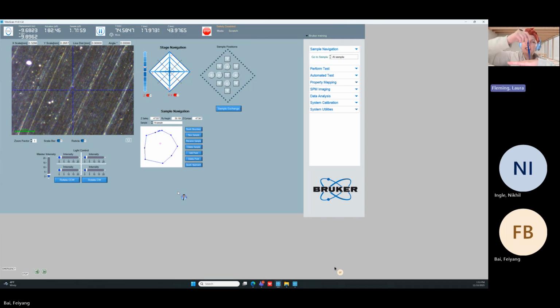If it has contacted the sample before, if this last contact height, Z contact, is correct, then it knows that it can go really, really fast till it's really close, and then it can go slowly and very gently touch the sample surface before performing the test. That's very important, that it's very gentle before performing the test, because we don't want to cause any plastic deformation.